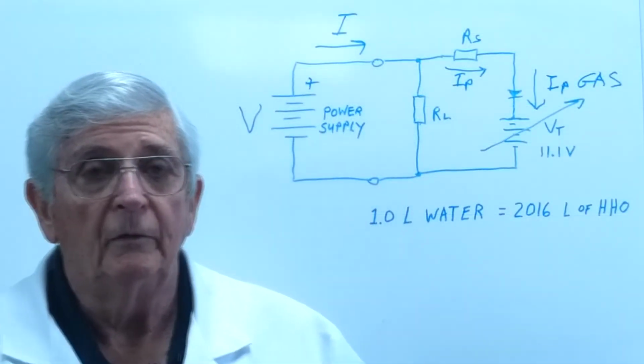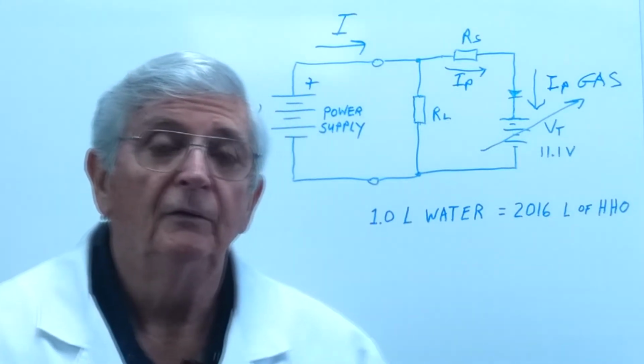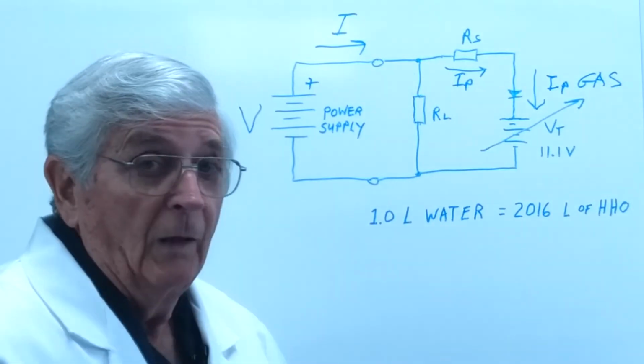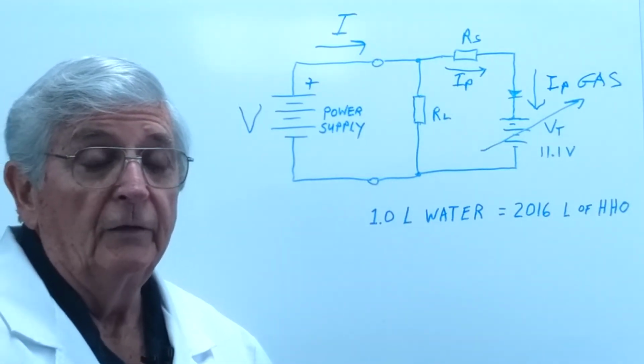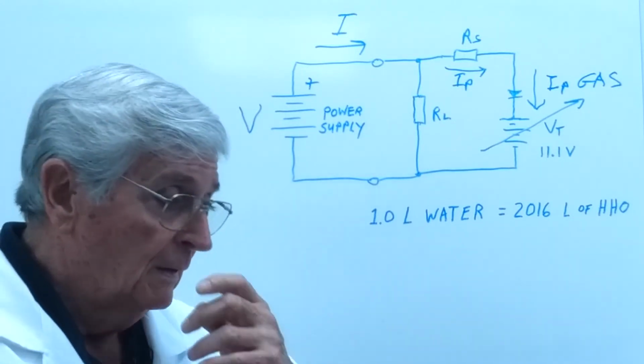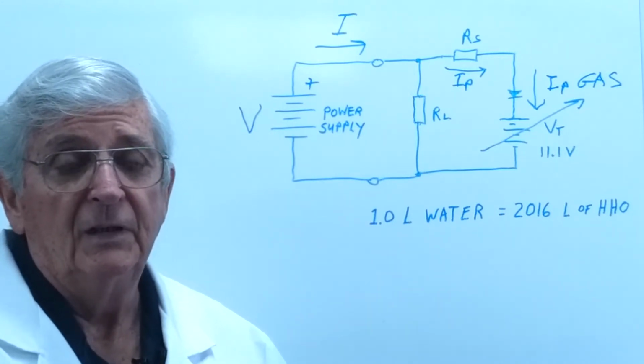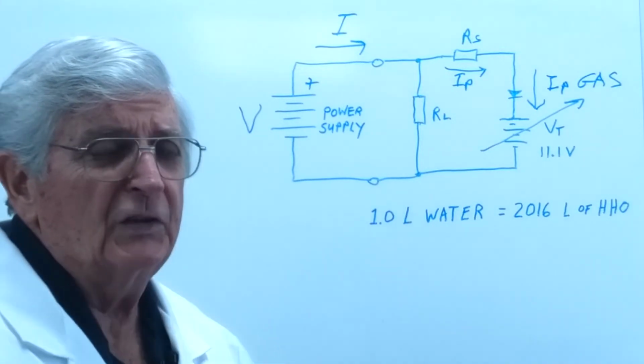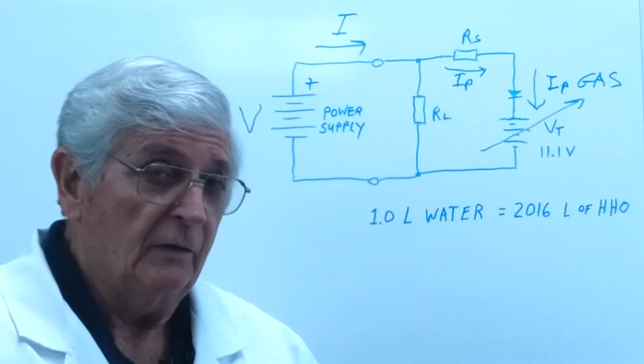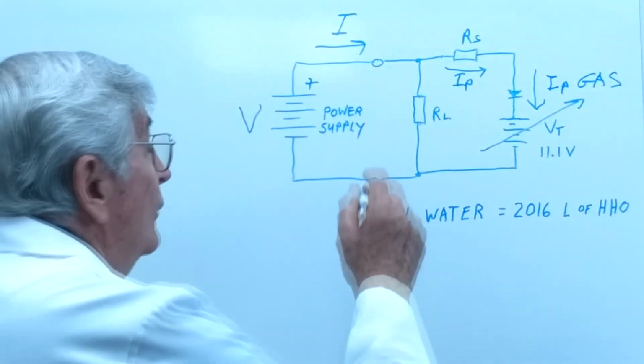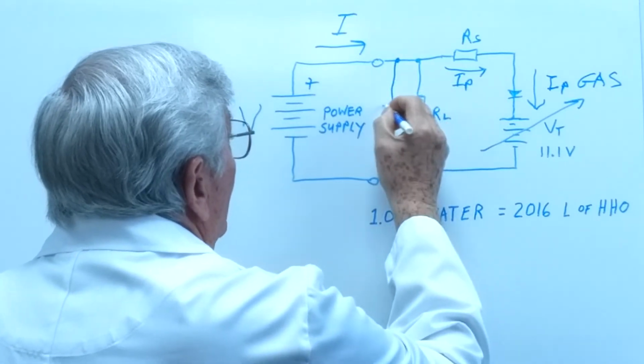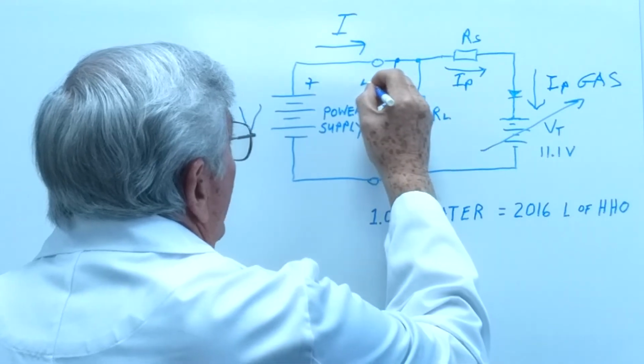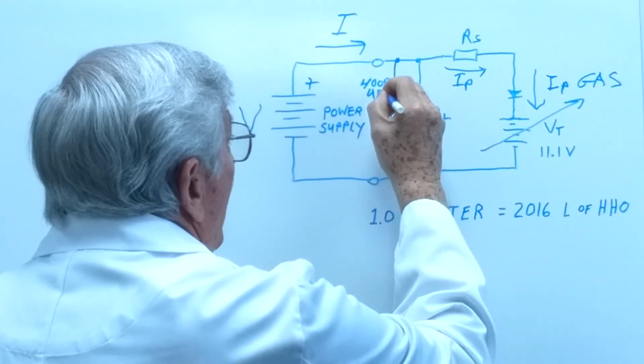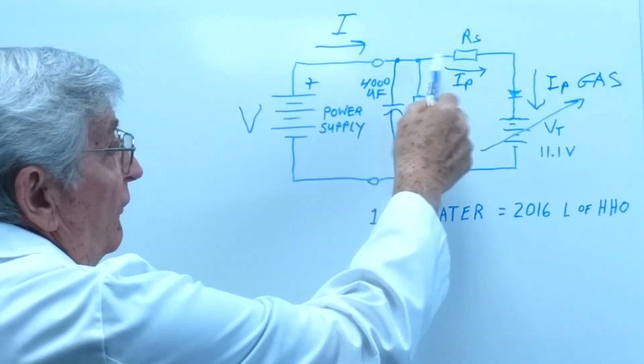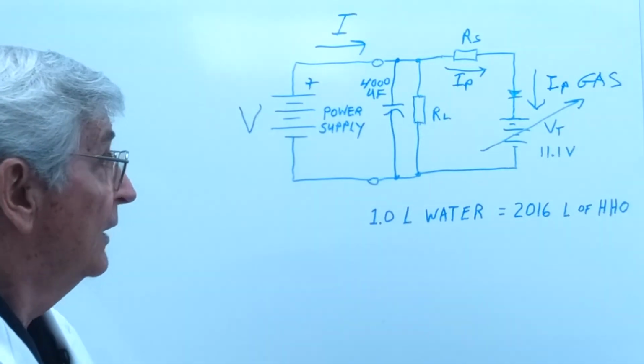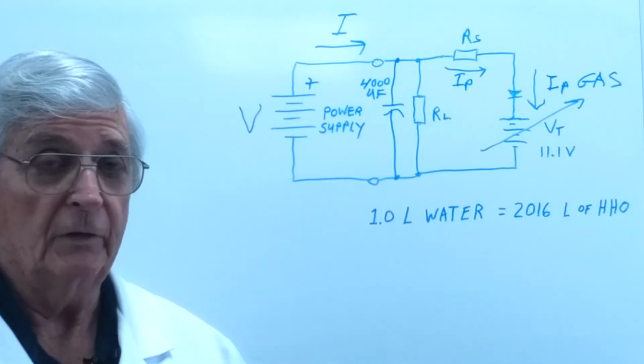Well, here's 2 other facts associated with generating HHO. While measuring voltage versus current, or vice versa, at very low currents, I was seeing big lags in the change in current for a change in voltage. That sort of indicates capacitance. And I did some measurements and found there's essentially a 4,000 microfarad capacitor in there. That'll have no effect on DC readings, but it does make measuring currents sluggish at low currents.